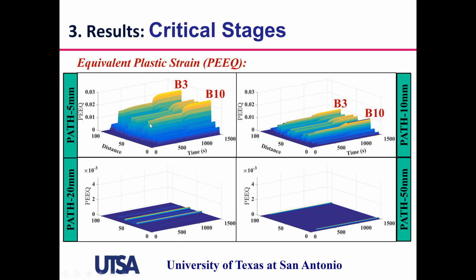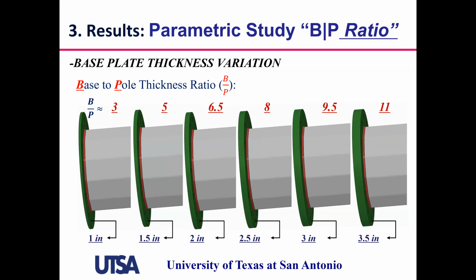So you can see here there are 2 spikes. One is when you dip the high mass illumination pole, and the other time is when you extract it from the bath. And the maximum plastic strains are observed at bends 3 and 10, which is in agreement with what has been observed during fabrication.